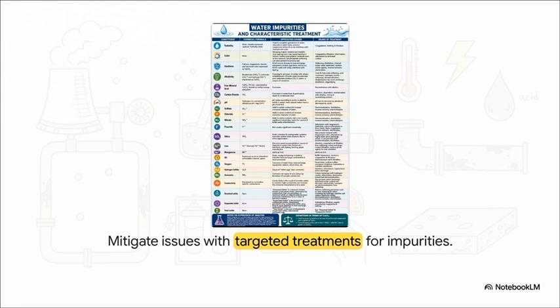If chlorides and sulfates start creeping in, you've got to rely on electrodialysis or distillation. If carbon dioxide is lowering your pH and you're risking FAC, you deploy aeration, deaeration, and neutralizing amines. The absolute secret to plant reliability is rigorous, continuous monitoring of cation conductivity and pH, and instantly applying these exact treatments the very second an impurity spikes.